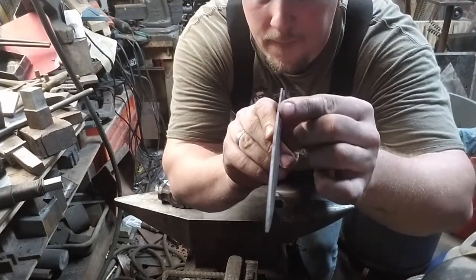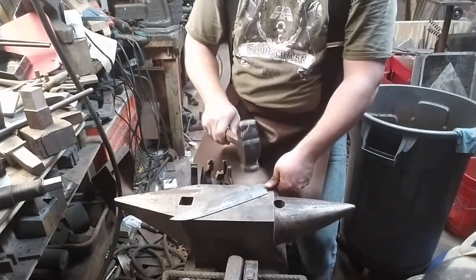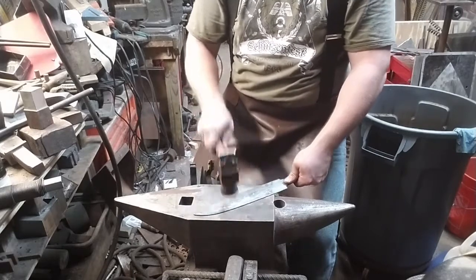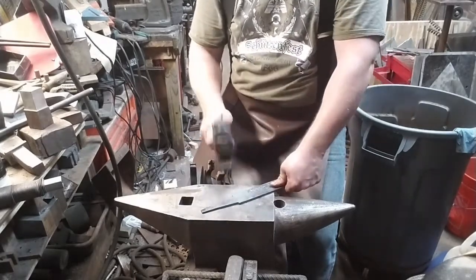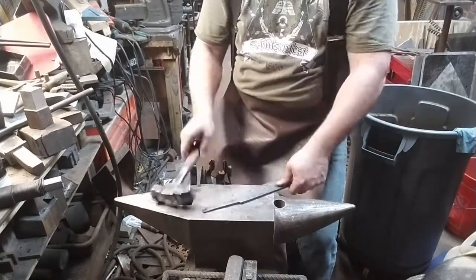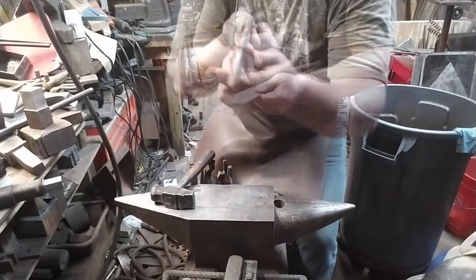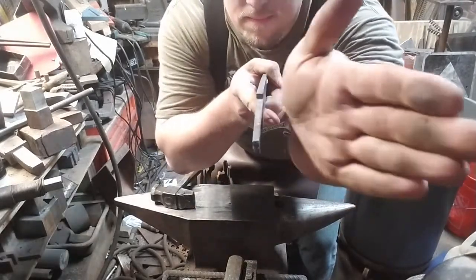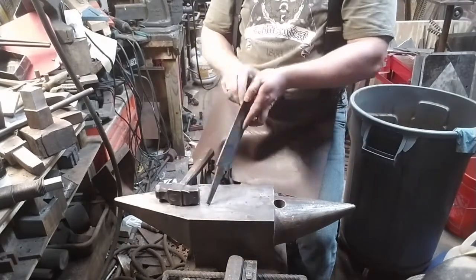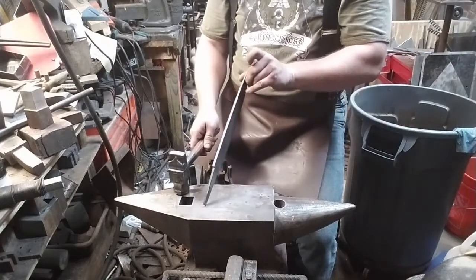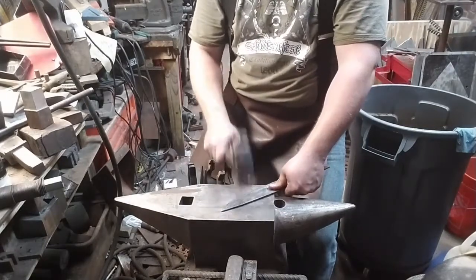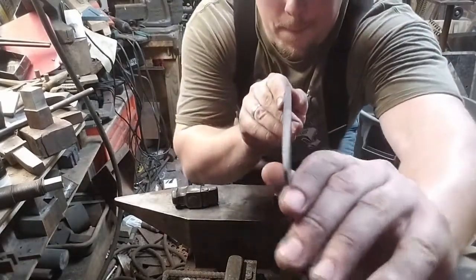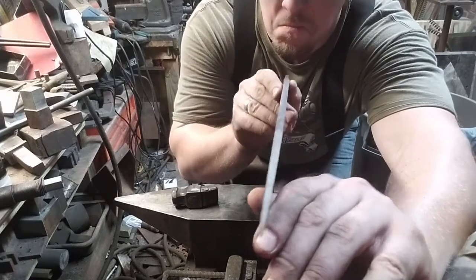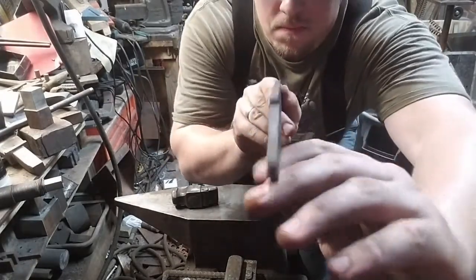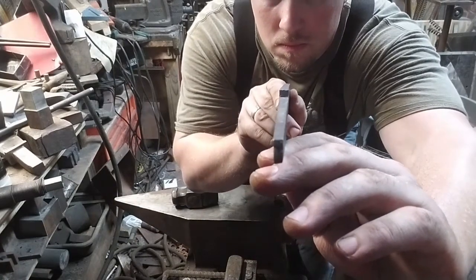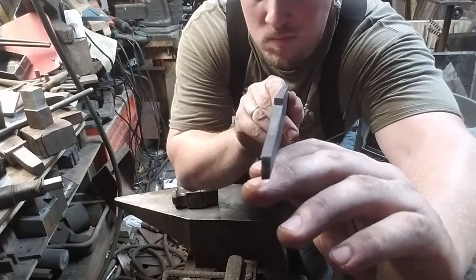Better. Still a few problems, but we're getting there. There are a number of ways to take any bends and twists out of a blade. You can do it at several different times during your process. You can do it during tempering. You can do it immediately after hardening, before tempering. I like to do it right here. The blade is soft. Each hammer blow does add stress to the blade, and so every time that you straighten, you need to normalize afterwards. But you should be doing several normalization steps anyway.